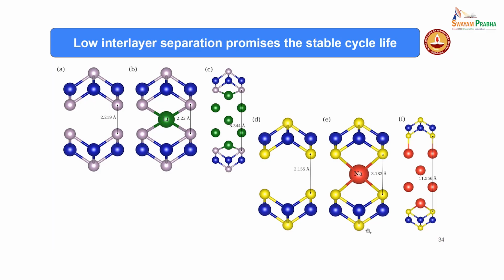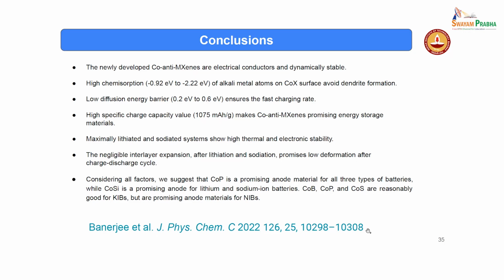So as a whole, these are the points that we learned today. First, the newly developed Co-anti-MXenes are electrical conductors and dynamically stable. So they are very good conductors, so we can use them. Similarly, we observed high chemisorption. That means they will not form any dendrites on the system. Next, a low diffusion energy barrier is observed for all of them. Since there is a low diffusion energy barrier, that means fast charge-discharge rates will be there. Specifically, high specific capacities are observed for lithium as well as for sodium, suggesting that they can be very useful.